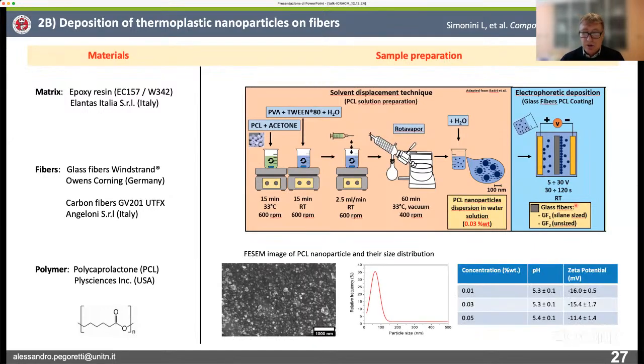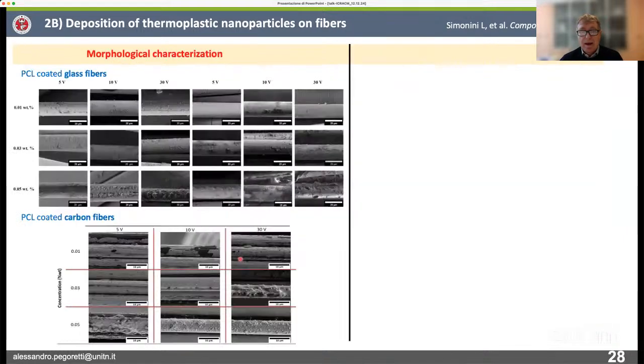Here you can see some data about the size basically of the particles. They were under 100 nanometers, so relatively small, without distribution, of course. And here you can see a picture of how the glass and carbon fibers can be coated quite efficiently by using this technique by relatively small particles of polycaprolactone.